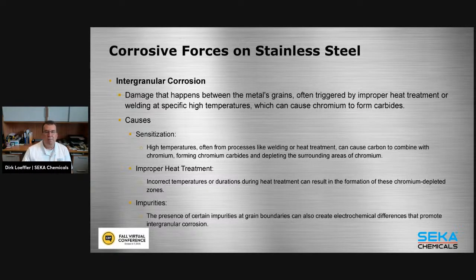Intergranular corrosion is kind of an interesting one. A lot of times, if you see in your equipment that the welds are starting to form rust first, or you see failure of welds, this is most likely due to what we call intergranular corrosion. If you weld improperly on stainless steel, the excessive heat can cause the carbon to combine with the chromium, creating chromium carbide, which is not forming a passive layer anymore. The chromium itself will form a passive layer, but the chromium carbide will not. Because you have these isolated areas, or potentially even larger surfaces of chromium carbides, you do see a lot of times corrosion occurring around welds.